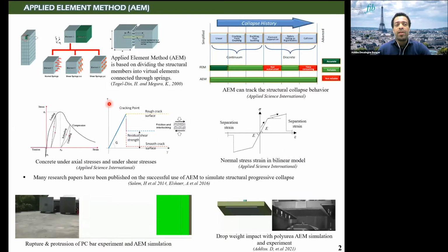In this study, we use applied element method to carry out a numerical simulation. It is based on dividing structural members into virtual elements connected through springs. These springs represent material properties and continuity between elements. The applied element method, AEM, can track structural collapse behavior, starting from linear crack initiation, propagation, element separation, and a complete collapse of the structure. These are material properties adopted in the applied element method. This is concrete under compression, tension and shear, and this is a bilinear material model. In the past, several research papers have been published on successful use of applied element method to simulate structural collapse behavior.